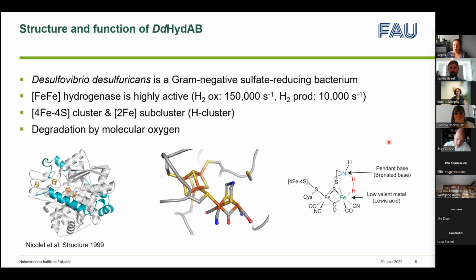So if we look at the mechanism of hydrogen splitting, to activate the small molecule hydrogen, a low valent metal is required that functions as a Lewis acid, and a pendant base, a Brønsted base, is required that is provided by the nitrogen at the top of the ADT ligand. So we have the distal iron and the ADT nitrogen that activate hydrogen.